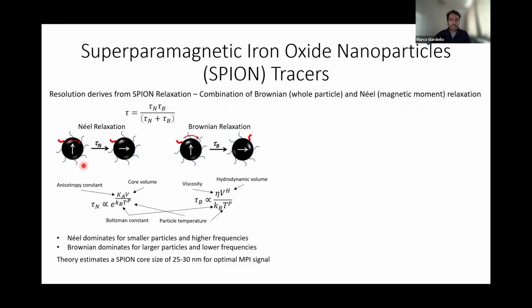Néel relaxation is the magnetic moment relaxation. It's like swapping north with south, so to speak. It's the internal rearrangement, as that rotates and oscillates in that oscillating field, whereas Brownian relaxation is the whole particle rotating. So you can see that the entire thing moves. It's based on diffusion and all this kind of stuff. But those two processes work in combination to give you your overall relaxation.